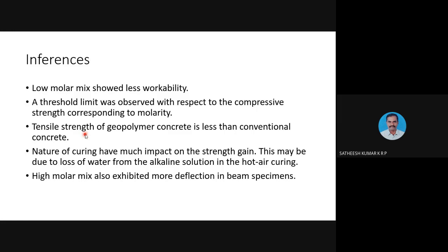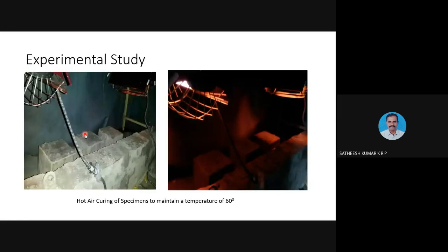And the comparison with respect to the nature of curing. In the previous slide, I have shown a method for hot air curing. This is an in-house setup for hot air curing, but this method of curing showed that it actually evaporates structural water from the elements. Whereas in the case of steam curing, we were able to achieve very good results. To compare the results, in this particular hot air curing method, we were able to get around 20% less than the results of the steam curing.